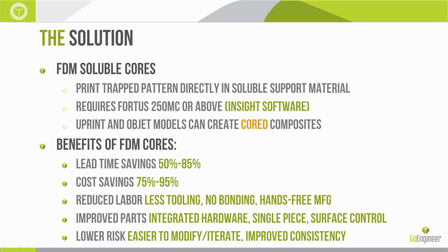The 3D printing process, just in general, normally requires a support material and a model material. And the model material is normally the end-use material. It's the ABS or the polycarbonate or the nylon. And the support material is there just so we can build overhangs and internal voids, and it's dissolved away later on. It's sacrificial. But within some of the software that we use, namely Insight, there's a checkbox that says invert materials. And if we check that box, we can actually print our end part, our goal part, in the soluble material. And then any support material that's needed would be printed in the end-use material, the ABS, for example.